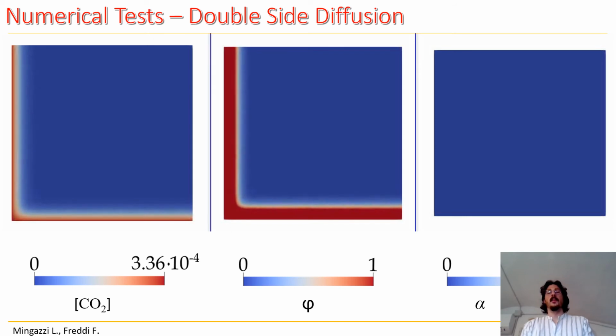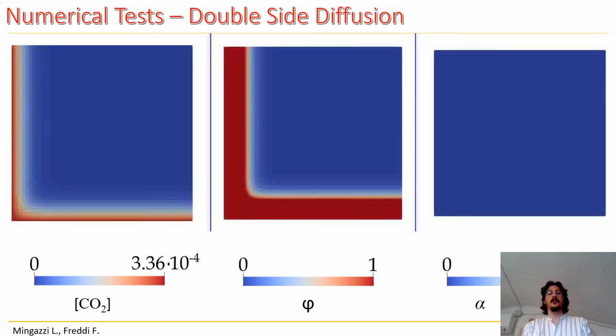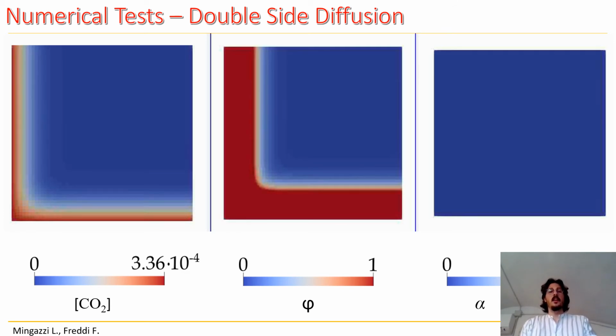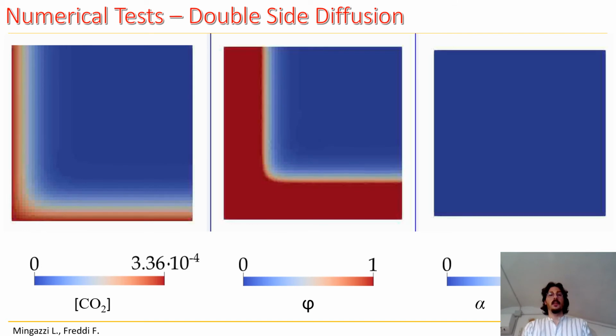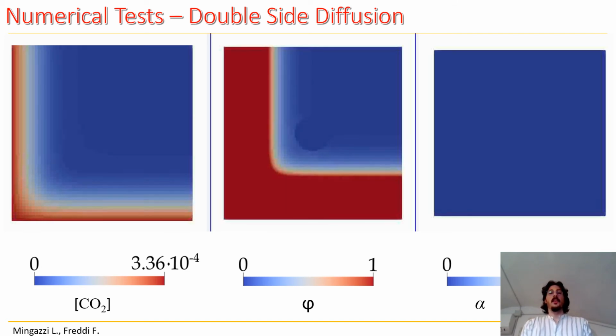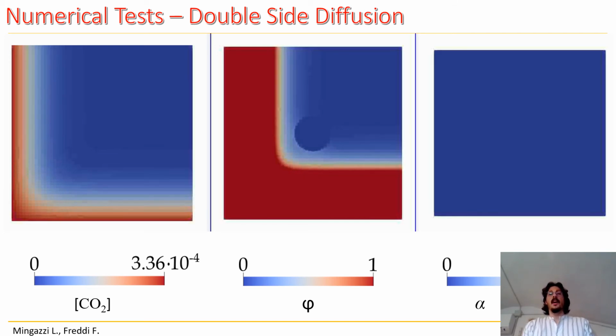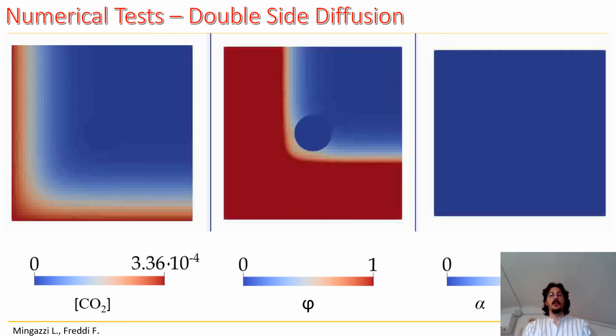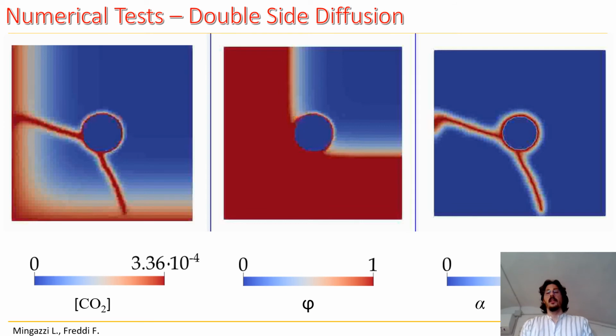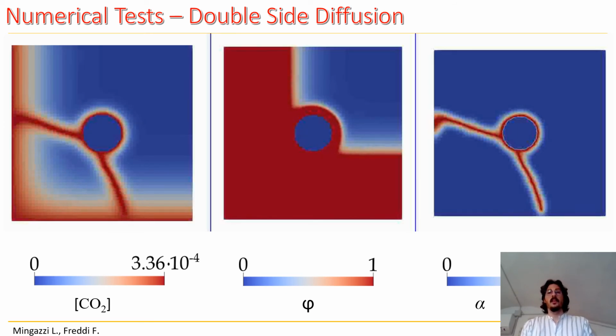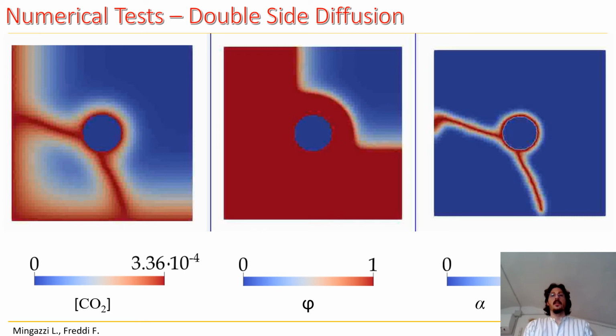The video reports the results for the double-side diffusion test we performed, and in particular we have on the left side the evolution of the concentration of the carbon dioxide. On the central panel we have the carbonation profile, while on the right panel we have the damage field evolution. It can be seen how the carbonation profile actively affects the crack pattern. Especially when the carbonation profile reaches the steel rebar, damage nucleates and evolves toward the side from which the carbonation profile reaches the steel rebar, as these are the areas where the swelling of the rebar starts earlier.